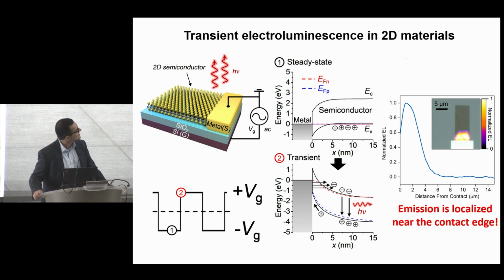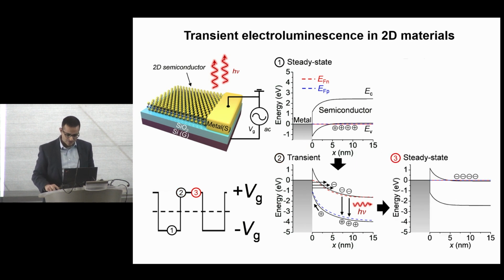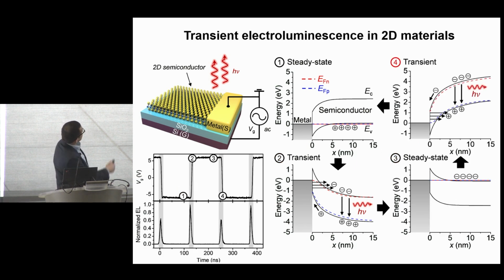It's just transient. We typically don't look at the energy band diagram under non-equilibrium conditions. And so what ends up happening is that when the band bending is like this, electrons will very quickly tunnel through from the metal to the conduction band, and at the same time, of course, some of the holes will leave. You form excitons, light comes out. The light then stops, you reach steady state, you flip the voltage again, light comes out. So you can look at the electroluminescence, and we can get this pulse emission. And so we have a pulse light source, and we can control, of course, the frequency and the emission characteristic by controlling our pulses.